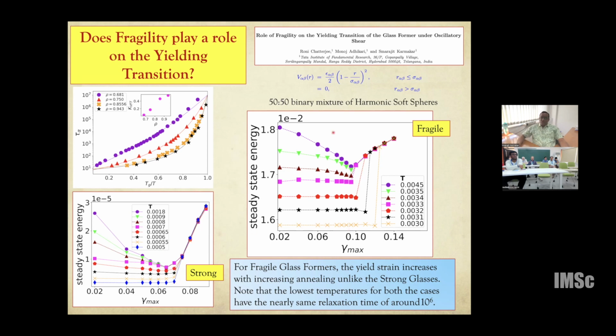At the same time, if you look at glasses formed from these fragile liquids, at this density 0.943, and look at the same phase diagram as a function of the oscillatory shear amplitude, what we see is that the yield point moves significantly with increasing annealing. So as you go to lower and lower energy states, your yield happens typically with a shear band formation, but at a strain which is much larger than what you get in the poorly annealed glass.